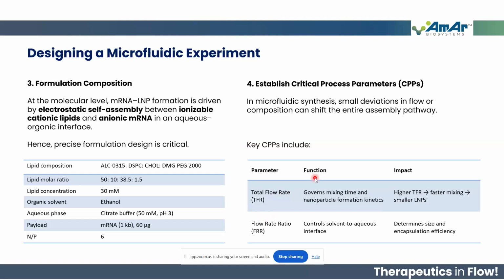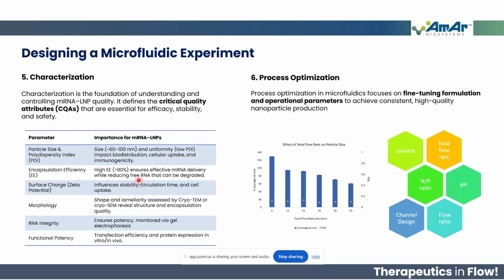And it's quite understandable that at a higher flow rate there is faster mixing, and this would lead to smaller lipid nanoparticles. And similarly, flow rate ratio essentially controls the ratio between the solvent phase, that is the organic phase, to the aqueous phase, and this also directly impacts the particle size and its encapsulation efficiency. And as mentioned earlier, different quality attributes of these particles can be characterized using different methods, such as particle size and polydispersity index can be determined using DLS. Your encapsulation efficiency can be determined through various types of assays, as well as the morphology and functional potency.